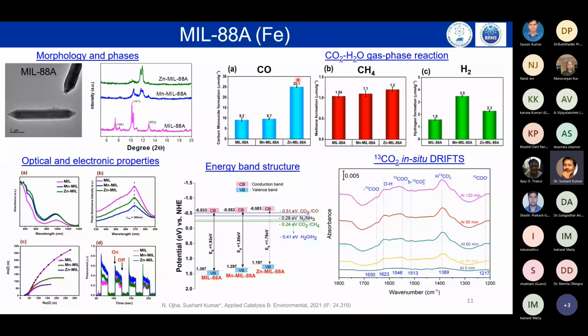Now, as I told you, this is an organic compound, so the carbon could come from the photocatalyst that we have prepared, or from the carbon dioxide. To really understand this, and to not consider the carbon coming from the photocatalyst, we performed the in situ DRIFTS in the presence of 13CO2, and this has shown a clear understanding of the mechanism. The clear presence of 13CO told us that yes, the reaction is feasible, the reaction is happening. The CO2 is taking up the electrons and is forming different species, which are vital intermediates to form the products such as CO and methane.